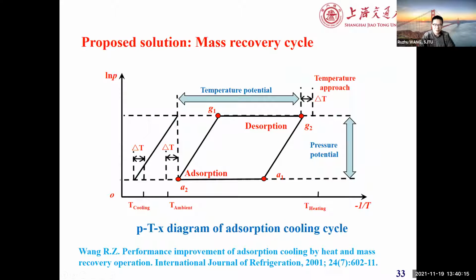But now we also developed it for the 2 beds, so not only heat recovery. So I proposed the solution, the mass recovery, because when one adsorber is at high temperature, high pressure, and another adsorber is at evaporation pressure, you still have a pressure difference. So in this case, I proposed to use the pressure difference. So this paper was published in the International Journal of Refrigeration.